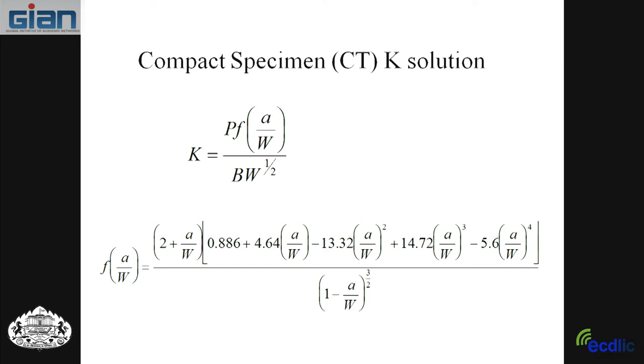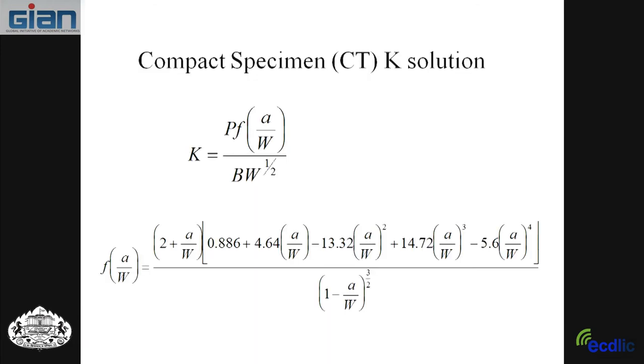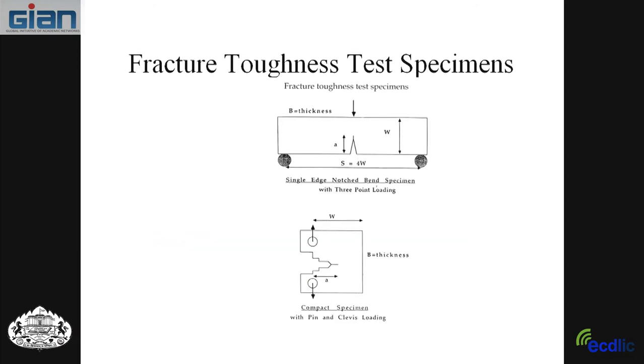Anyway, the solutions for K have this F function, which is a real bad polynomial. You're going to calculate that polynomial all the time, and it's a pain in the neck for number one. Number two, I never go through it and get the right answer because I make a mistake somewhere along the line. So I did print out this table. This is this F function printed out in a table. If you rearrange this, take B square root of W times K, and then divide that by P, then B square root of W K divided by P is a little f function. So it's this column. It's a little f function. It started with a over W, which in this specimen is the crack length from the center of the pinholes to the tip of the crack. Here it's from the edge of the specimen to the tip of the crack, and then W is the width here. W.